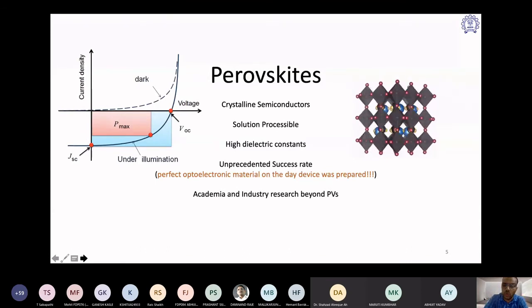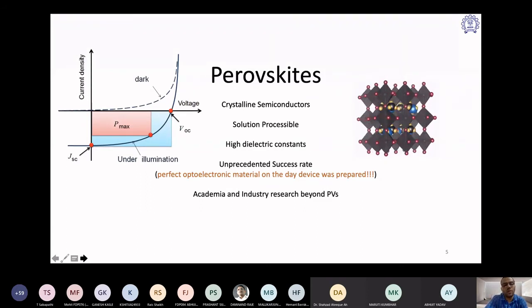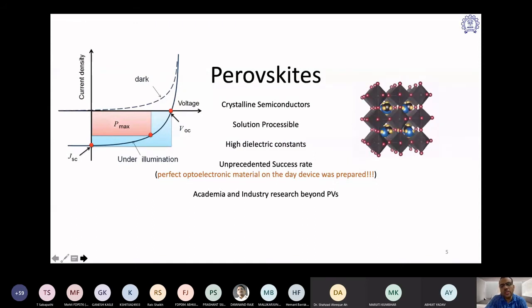The formation energy is very low, and so you can get a solution processable, highly crystalline film, very shiny, very nice film, and that shows fantastic solar cell performance, a kind of unprecedented success rate, and perfect optoelectronic materials on the day the device was prepared. I'm putting lots of exclamation marks here. Why? Because as I was telling, the formation energy is very low, so the breaking energy is also low. The things which can be made easily can be broken easily.